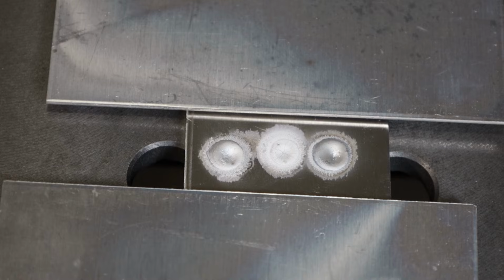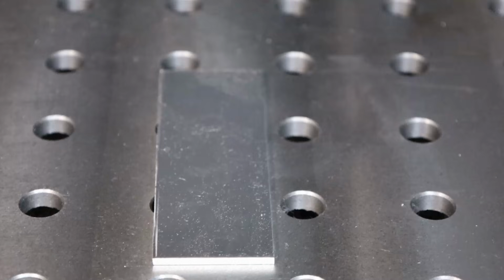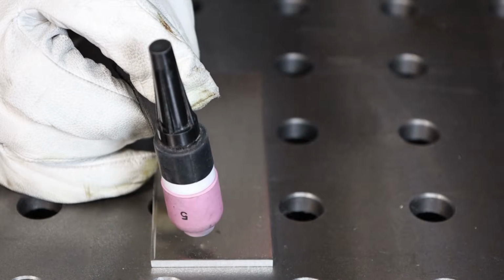So once you're able to form a weld pool, let's talk about your torch angle, because this is pretty important. Right, so as you weld along, it's important to tip your TIG torch a little bit, right? You can run almost straight up and down, but tipped just slightly in the direction that you're going to travel. You don't want it to be tipped backwards. It should be pointing forward, and that's going to work out better for you, because as you start to add filler metal, you want to come in here about perpendicular or even a little bit higher from the torch, and this is going to let you do that, to add that in.